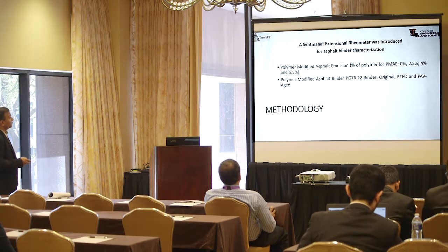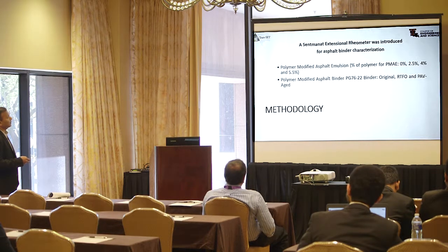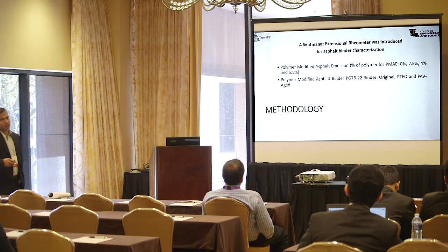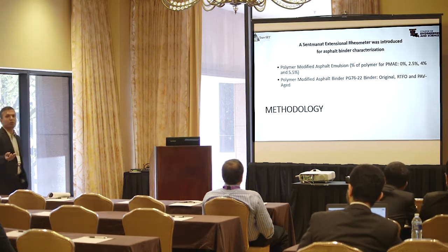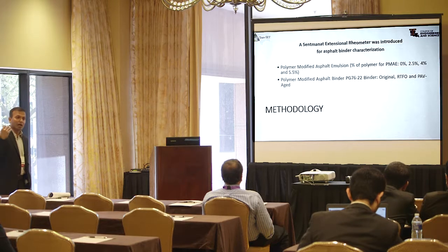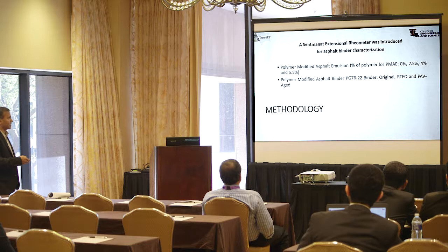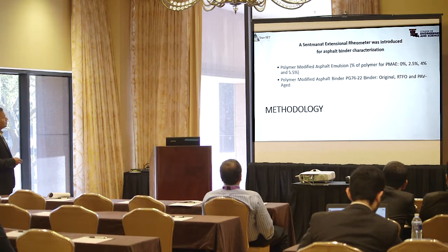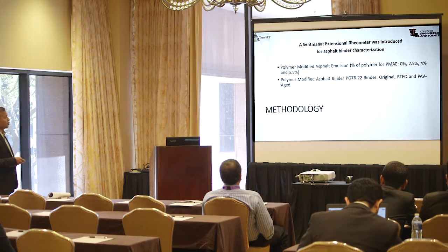So as I kind of write this one, after my Sentmanat Extensional Rheometer was introduced for asphalt binder characterization. This is what we came up with: we'll use that, which is being used for polymer, in our DSR and try to do the extensional deformation test. So we did that, and also we used polymer modified asphalt emulsion that has 0%, 2.5%, 4%, and 5.5% polymer.